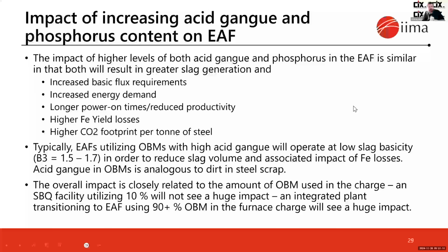So let's talk about some of these quality concerns. What we've seen worldwide over the last 15 to 20 years is a steady increase in the phosphorus level in blast furnace pellets. That's because we tend to mine out the best quality early in the life of a deposit, and now we're getting into blending in other ore that, while its properties are quite good, has higher phosphorus levels. So both acid gangue and phosphorus increase basic flux requirements, increase energy demand, extend your power on time, result in higher yield losses, and result in a higher CO2 footprint per ton of steel.